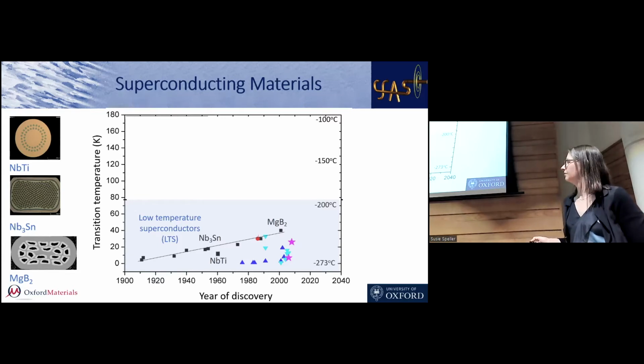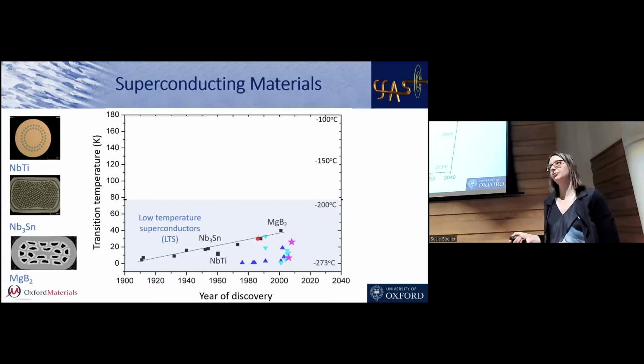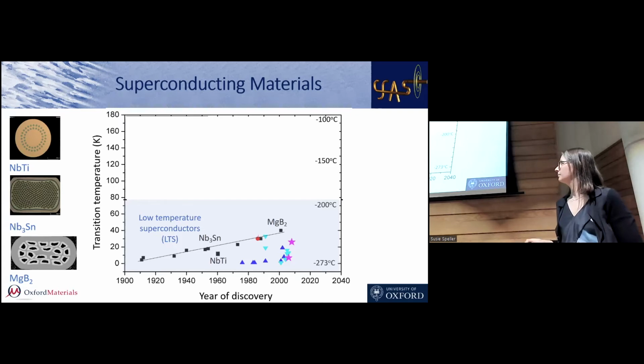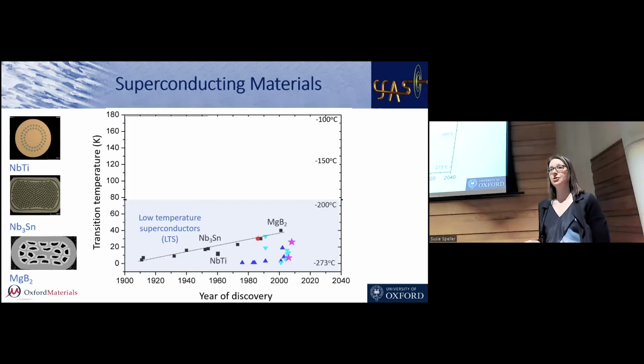But quite soon after that, they realized that they didn't need to be elements at all. They could mix them together and make alloys and create better superconductors, so ones with higher critical temperatures. So niobium tin and niobium titanium, these are rather special superconductors because they're ones we can go and buy in the form of wires. So they're here on the left-hand side, niobium titanium and niobium 3 tin. So you can go and buy those commercially.